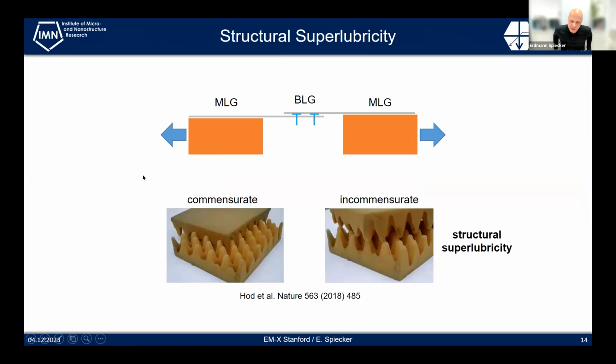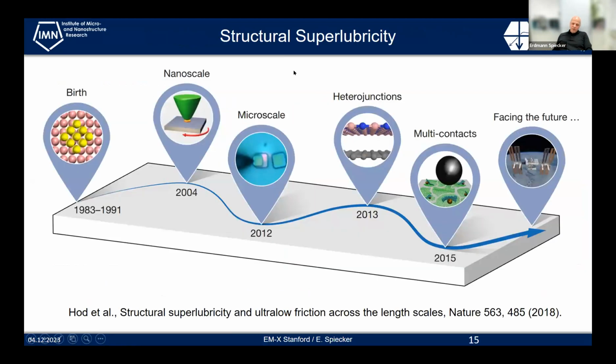Now I'll come back to the experiment I want to talk about, which is also about dislocations, because a twist dislocation network is also composed of dislocations in bilayer graphene. And I just want to mention briefly that structural superlubricity originated from a paper by Aubry in 1983, and he proposed that under certain conditions there's a transition to superlubricity, so frictionless sliding, if you have an incommensurate structure between the two parts that slide on top of each other. And this was nicely demonstrated experimentally by Dienwiebel in a famous experiment on graphite.